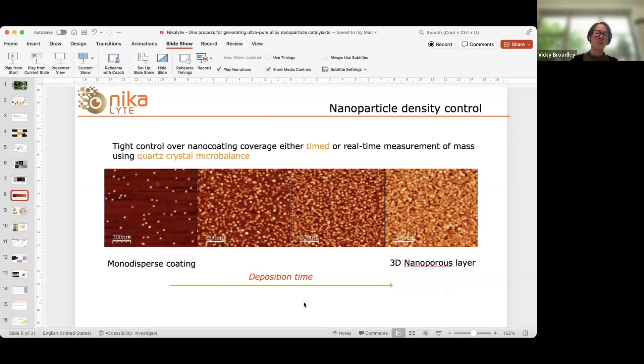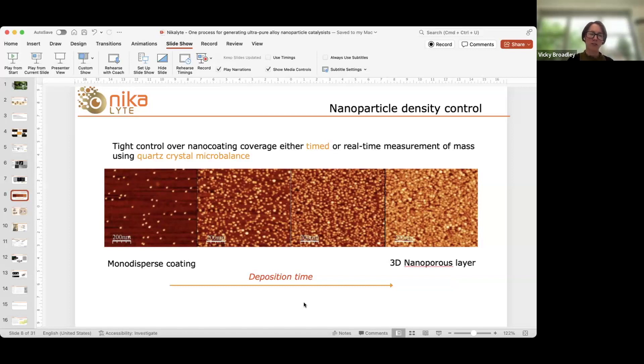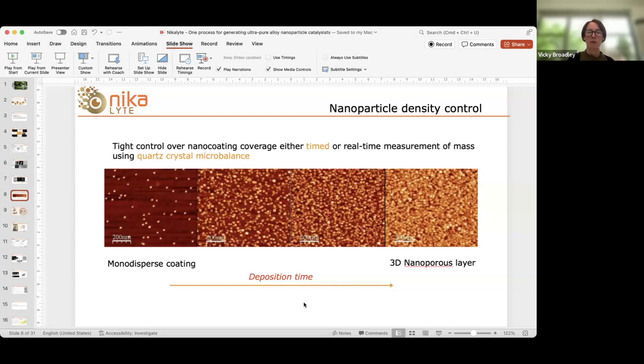Another feature of this technique is control over density and loading. Because it's a vacuum technique, we can use a quartz crystal microbalance — a gold-coated quartz crystal inside a vibrator that measures the thickness or weight of material deposited by monitoring the frequency of vibration. As frequency varies, that tells you there's more weight on the surface. We have a quartz crystal microbalance sitting next to our sample in the chamber during deposition. This gives us real-time information about the coating density, allowing us to account for any changes in deposition rate and reproducibly create the same loading density from sample to sample.